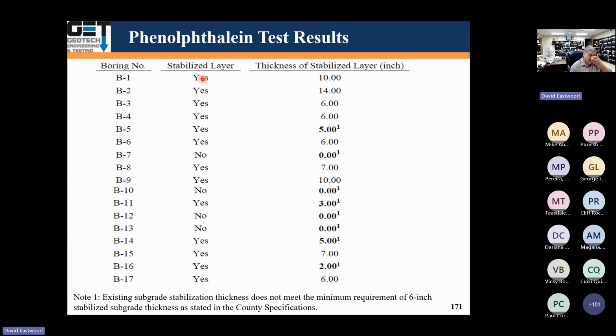Some of them had stabilized layer. Like this one didn't have. B7, we had no stabilized. And there was actually no stabilized area at B7. Okay. B10 had no stabilization. B12 had 0. B13 had 0 stabilization. And some of them had like 2 inches of stabilized subgrade. Some of them had 10 inches. Some of them 14 inches. Some of them had no stabilization.